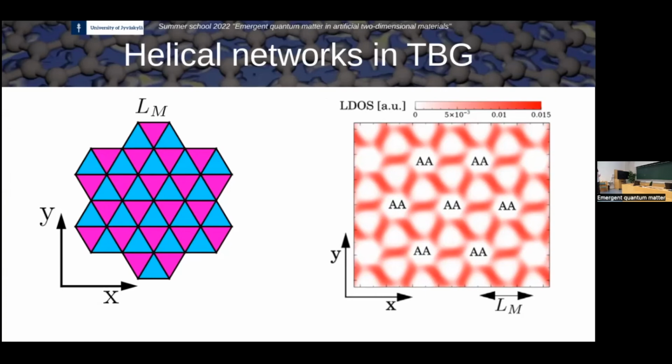Yeah, that's a very good question. The short answer is that here it doesn't happen because here you don't have, let's say, local ferroelectric polarization. So in those systems, you can, let's say, move domains with a gate because you have finite electric dipoles that come from the location of the atoms themselves. So the electric field couples directly to that. Here you don't have a finite polarization, therefore the domains do not move.